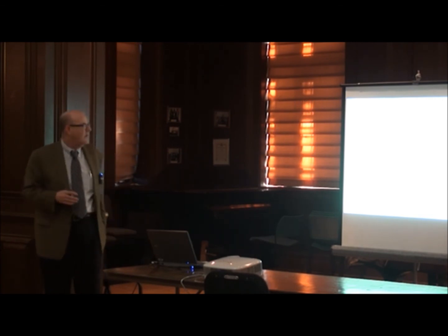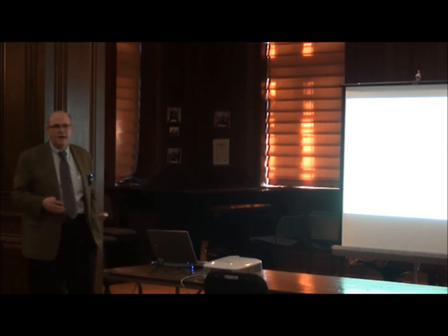Because we're assuming in a nicely lubricated system, the asperities aren't actually touching anymore. It's basically the shearing of the fluids and that related that. As the interface goes mixed and you get asperity contact, then we start to move back into the dry sliding mechanisms of just real area of contact deformation and plowing. So you net it all down right here.